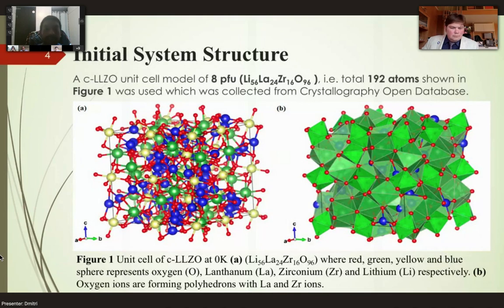This is the initial system structure for our model. We have used 8 formula units, so we have used 8 combined cells as a unit cell, which has 192 atoms, where we'll be mainly focusing on the blue. We have 56 lithium atoms here, but for these 56 lithium atoms, we have 120 available spaces in this unit cell, and the available space for these lithium atoms comes from 24D tetrahedral and also from 96H octahedral sites. Next, please.